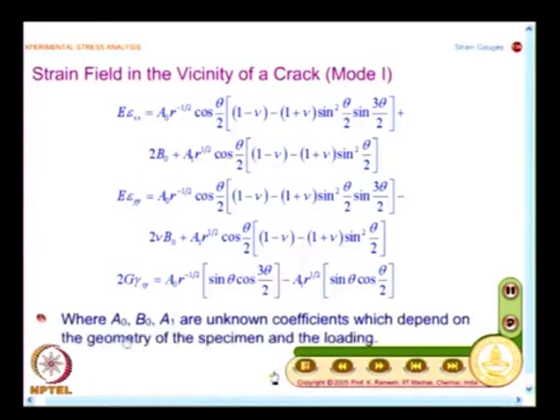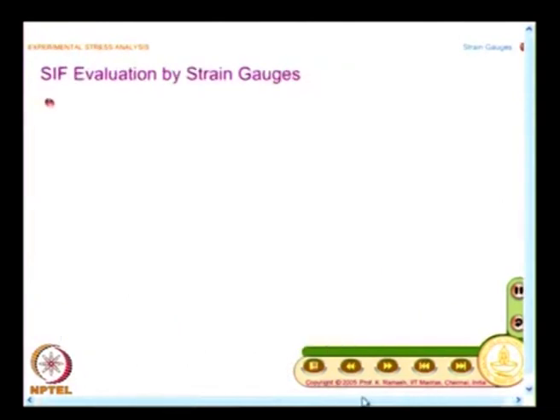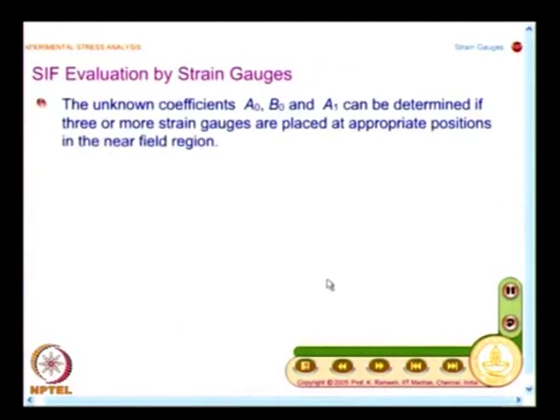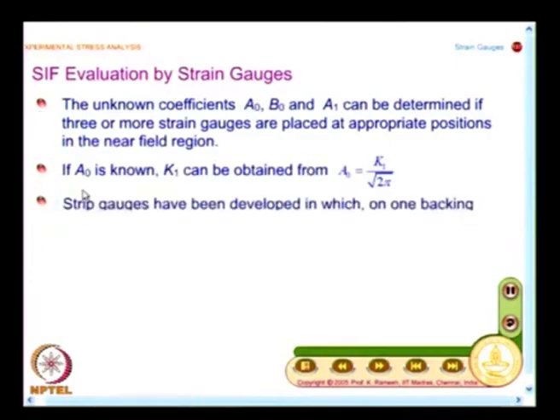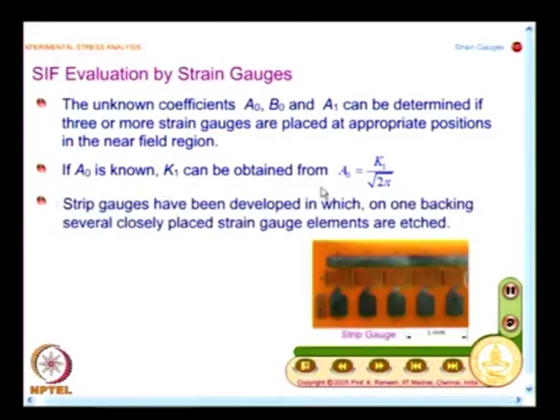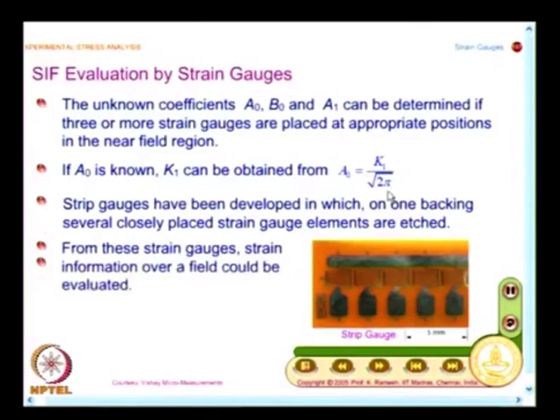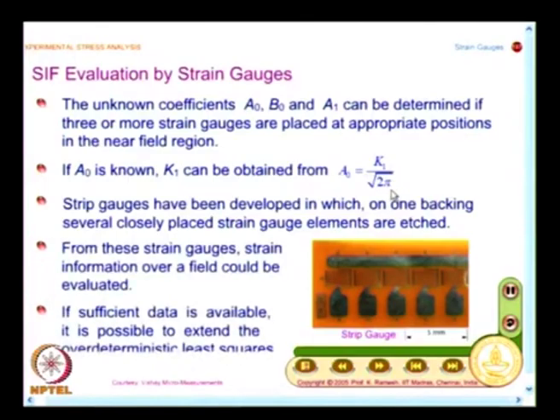And this is what is summarized here. A naught, B naught and A1 are unknown coefficients, which depend on the geometry of the specimen and the loading, and we will knock off the other terms, leaving only A naught. If A naught is known, K1 can be obtained from A naught equal to K1 by root of 2 pi. This is what I am going to aim at.